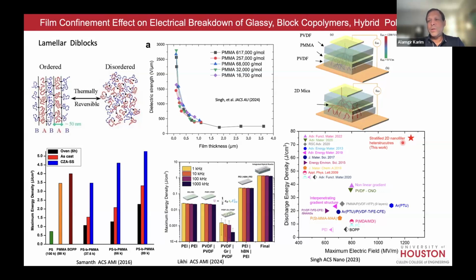As I said, a huge amount of work in nanocomposites with spherical particles does not do well on the breakdown voltage, and so the energy to breakdown is low. So you lose out on the square of the breakdown voltage, but you gain on the dielectric constant. You don't gain much, but with 2D sheets, you gain. It's a win-win situation, and that's really the difference we have made here.